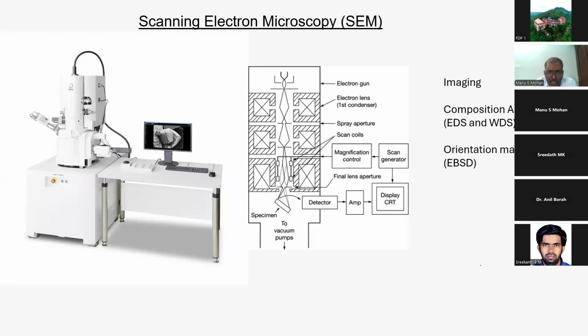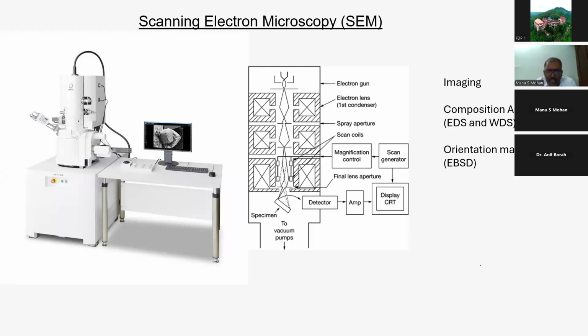intensity of that element. And then you have the famous Castaing's equation, which says that the intensity of the particular element in the specimen, divided by the intensity of the element in the standard, is proportional to the weight fraction of that element in the alloy times the ZAF. ZAF means the atomic number, absorption and fluorescence factor corrections. So this is how the SEM EDS works.